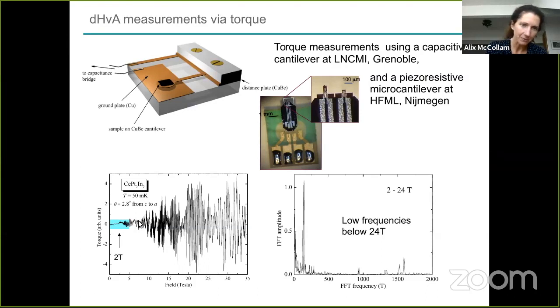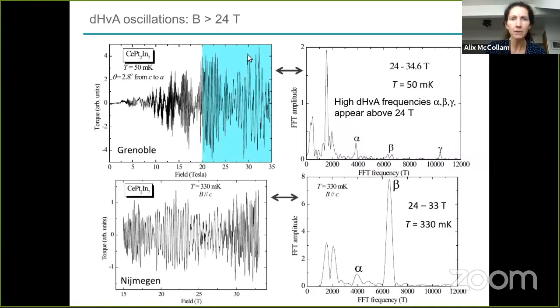So it's this region of the oscillations there. We see a very low frequency here, and then a few at 1.5 kilotesla frequencies, so quite low. When we look at this region, which is above 24 Tesla, we just detect it. It wasn't a number that we picked, but we did analysis over the whole field range sequentially, and we found that there was some change in the spectrum at 24 Tesla.